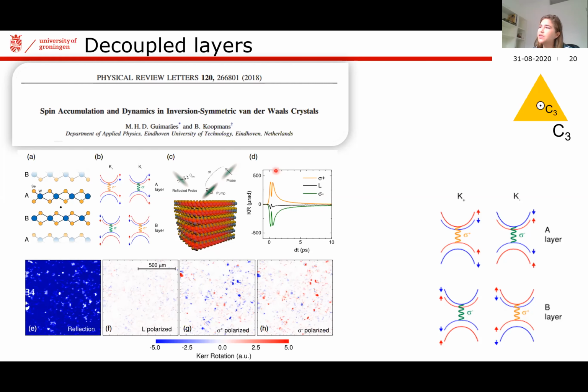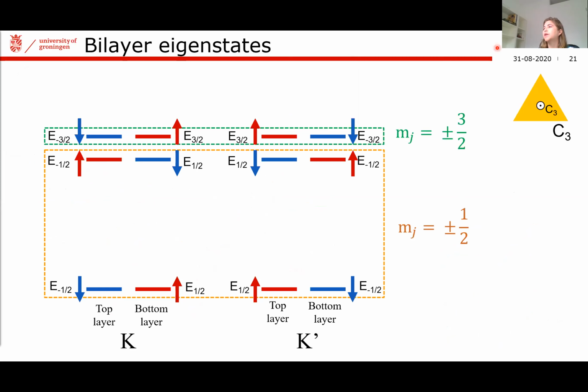So this gives rise to an electronic structure that looks like this, where you'll recognize some of the properties that you see in the monolayer already. Right? So now you do have some spin valley coupling in each of the layers, but they're opposite, therefore opposite K and K' sides. Now again, these top states transform as wave functions with mj equals plus and minus 3/2, whereas the orange states transform as wave functions with mj equals plus and minus 1/2.